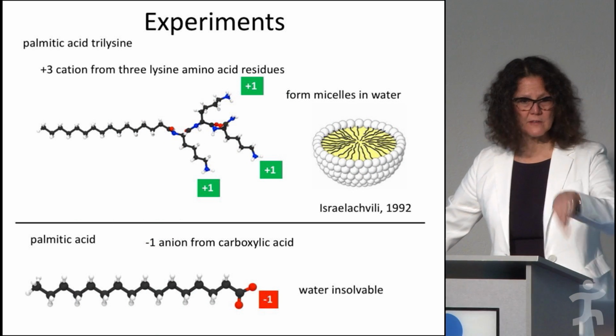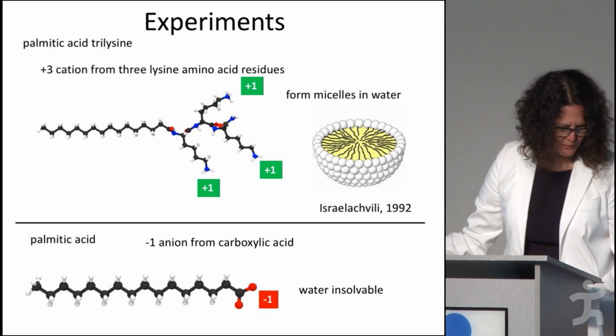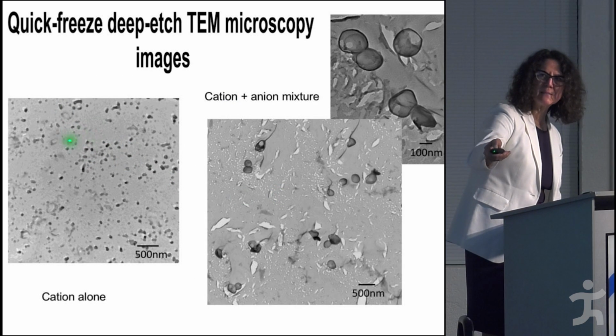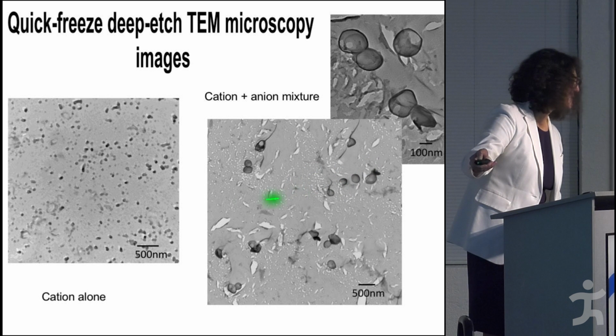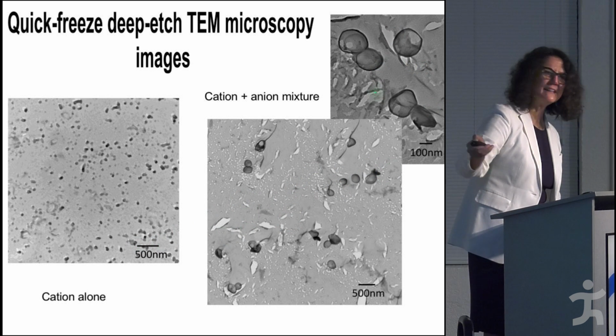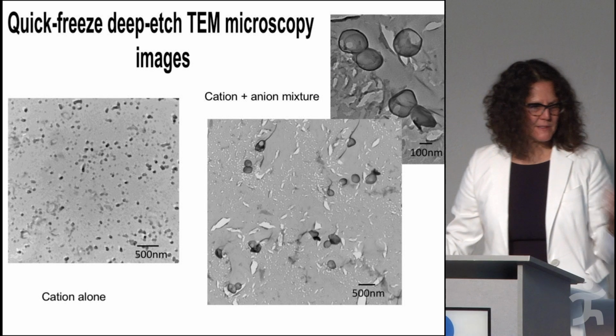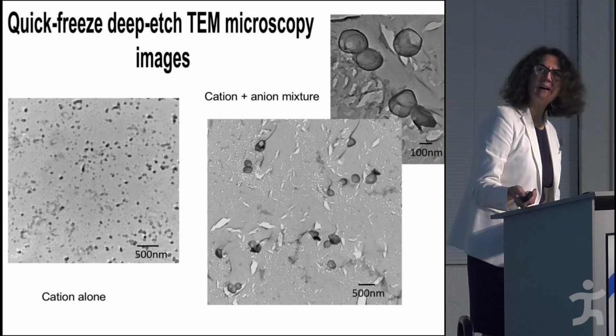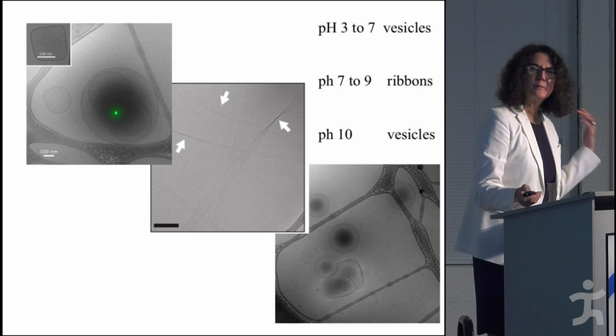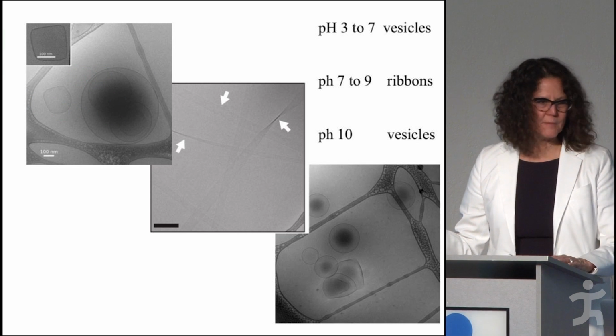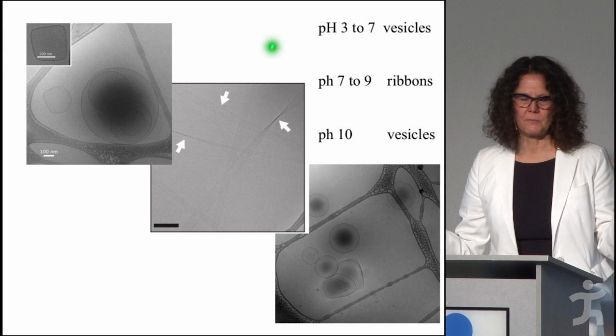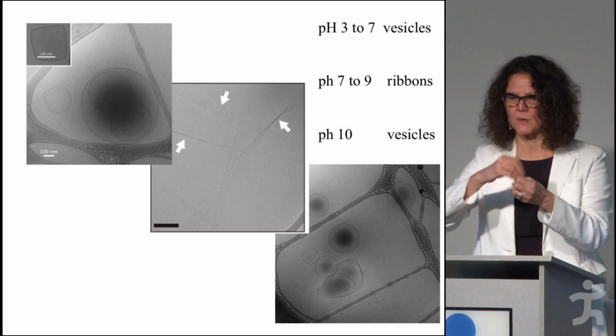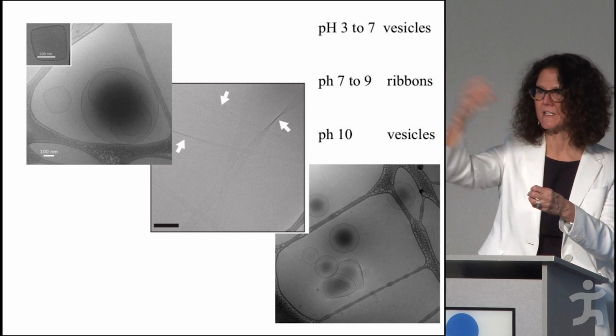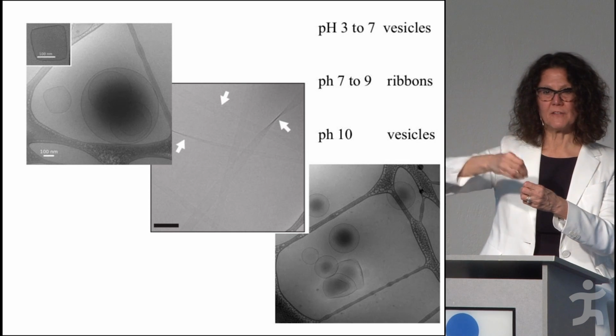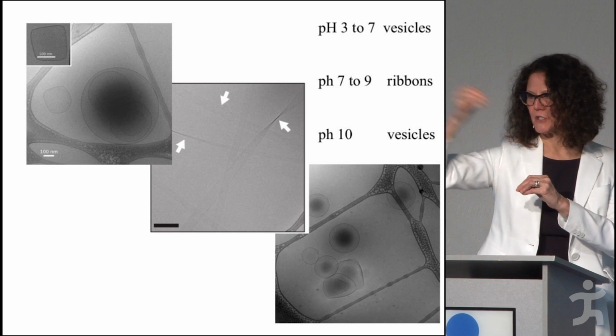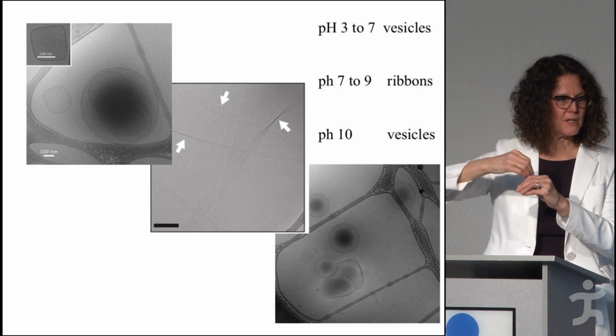But if you just mix them, then instead of just these micelles, you will form these vesicular structures, these shells. Okay? So these are the shells that I was discussing, that they form in the beginning. But what we find surprising is that these shells form only at certain pH. pH is associated with the concentration of H+ in a solution. So depending on the amount of them, you can dissociate more charge or not.